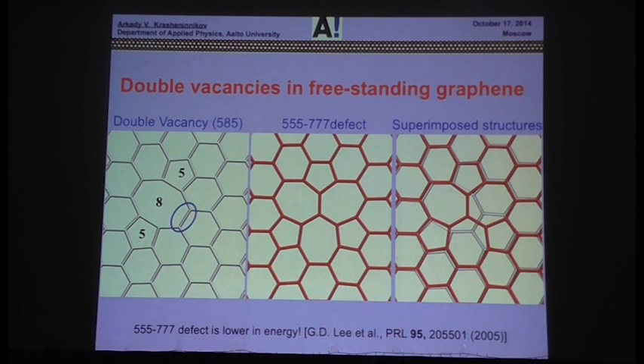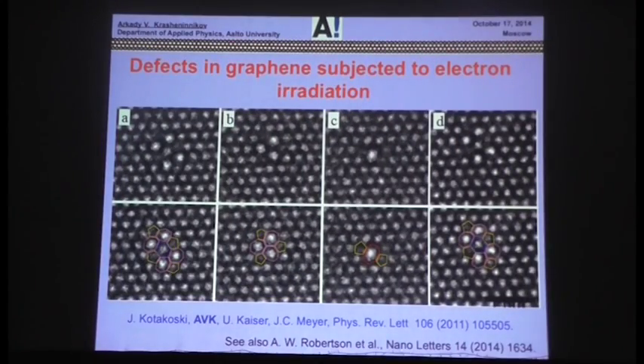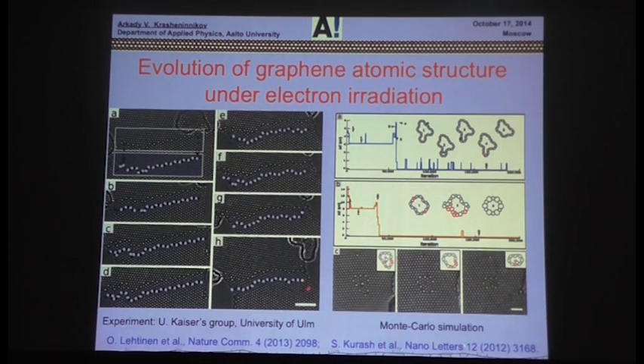And this may also work in more complicated defects. This is a divacancy. You take this bond, you rotate it, and you get a constellation of hexagonal rings, 5-5-5-7-7 defects. Energy goes down, in fact. And essentially, these are all defects which my co-workers have seen in the experiments. For example, this original divacancy is a 5-5-5-7-7 defect. The next one, and so forth. Moreover, this way you can change the grain boundaries in graphene, or even small grains can completely annihilate. It's just an example of what the electron beam does to your sample.